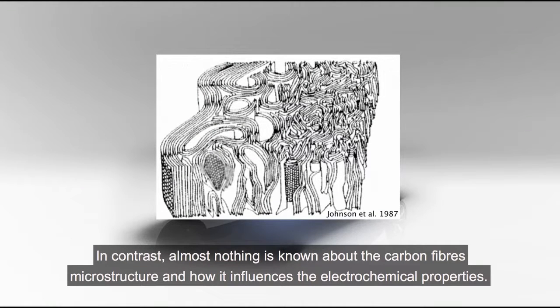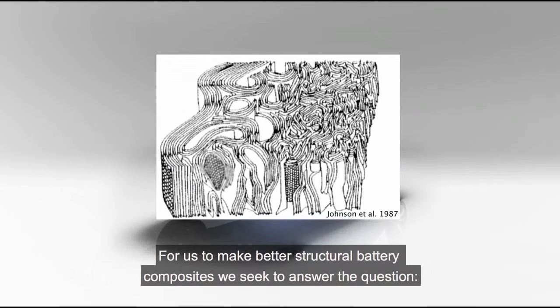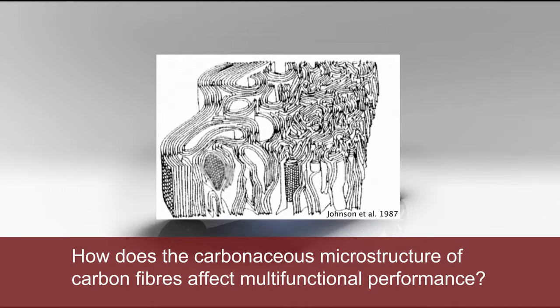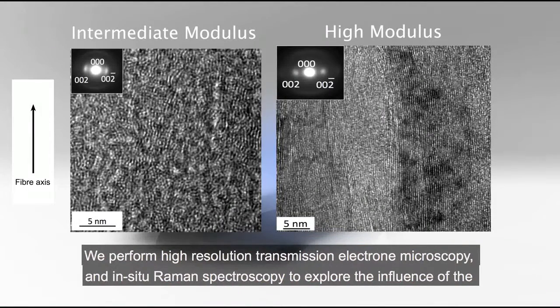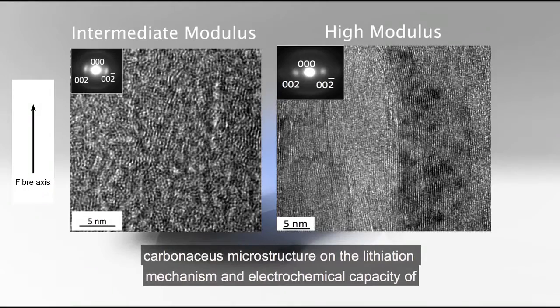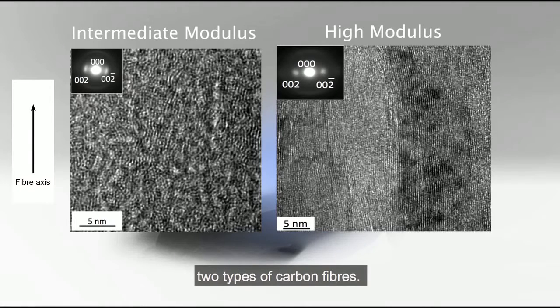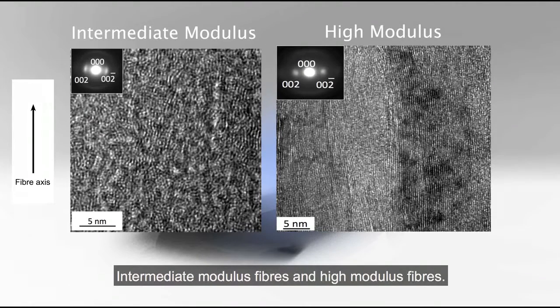In contrast, almost nothing is known about the carbon fiber microstructure and how it influences the electrochemical properties of the fibers. For us to make better structural battery composites, we seek to answer the question: how does the carbonaceous microstructure of carbon fibers affect multifunctional performance? We perform high-resolution transmission electron microscopy and in situ Raman spectroscopy to explore the influence of the carbonaceous microstructure on the lithiation mechanism and the electrochemical capacity of two types of carbon fibers, intermediate modulus fibers and high modulus fibers.